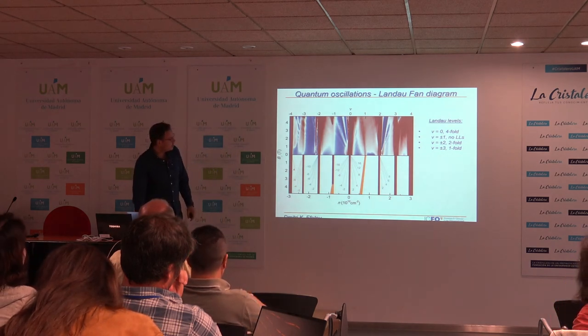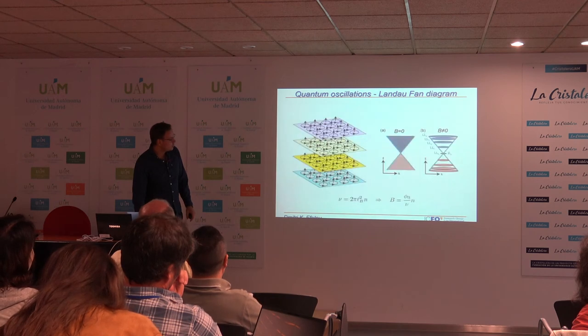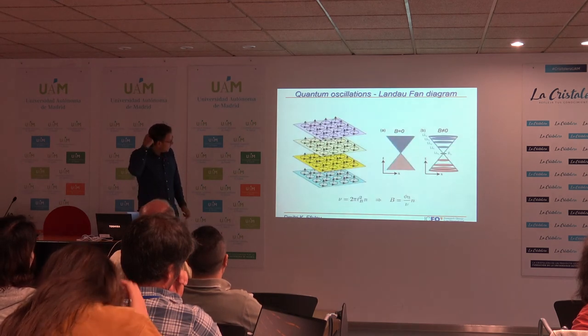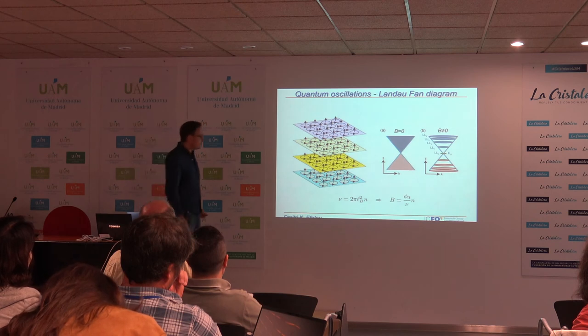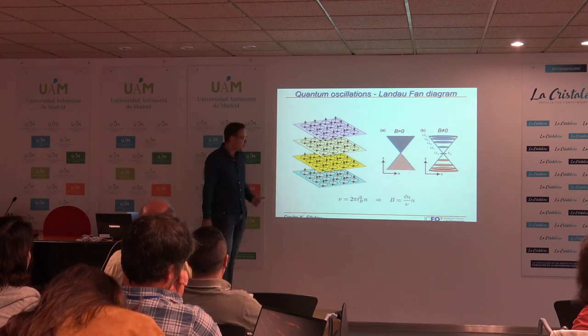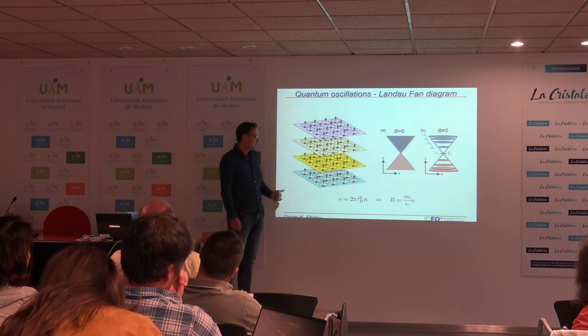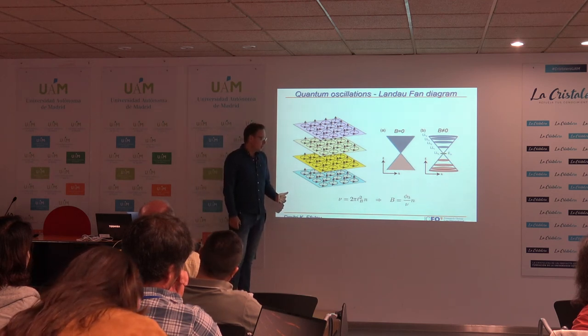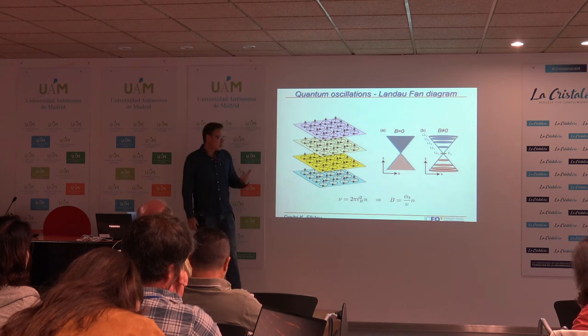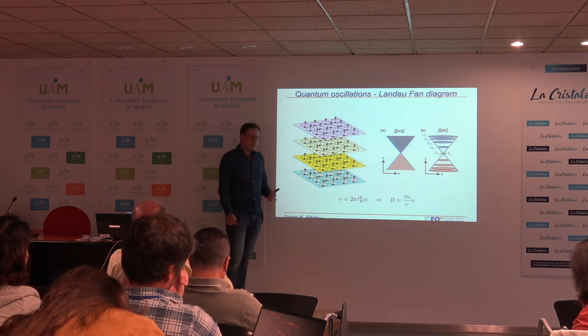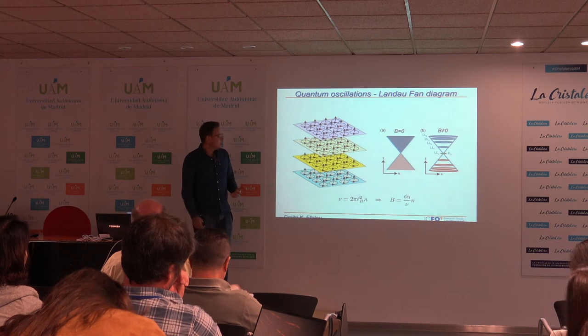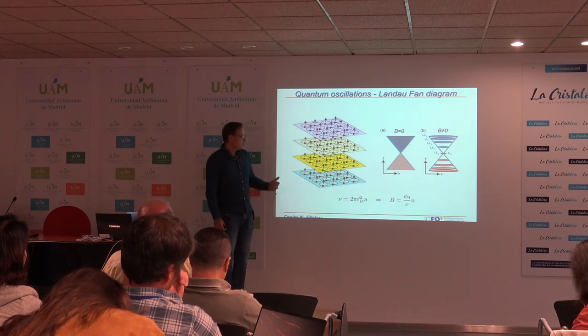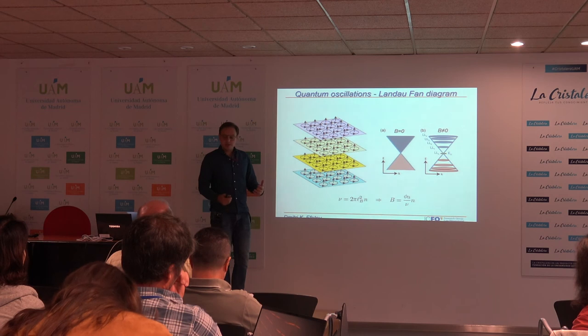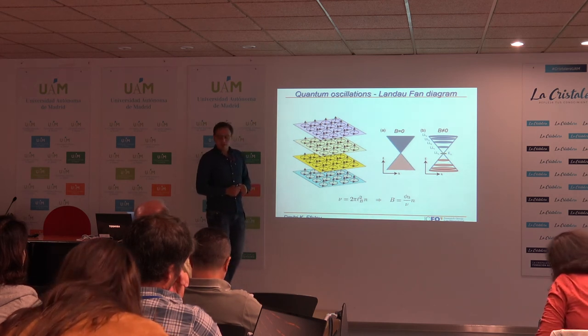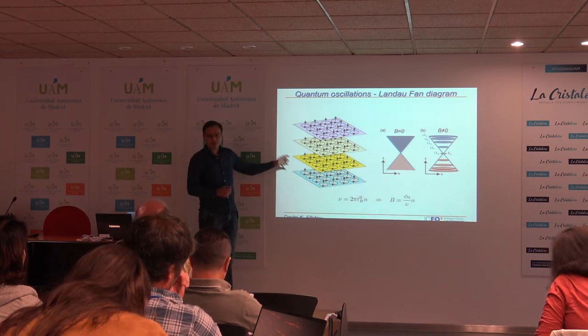Okay? And I'll give you a reason why we see straight lines in the Landau levels, and really this just comes from the Landau level quantization, where each Landau level can take so many electrons, and when we increase the carrier density, we can fill up those Landau levels. And when we increase the magnetic field, we can also pack more electrons into each individual Landau level.